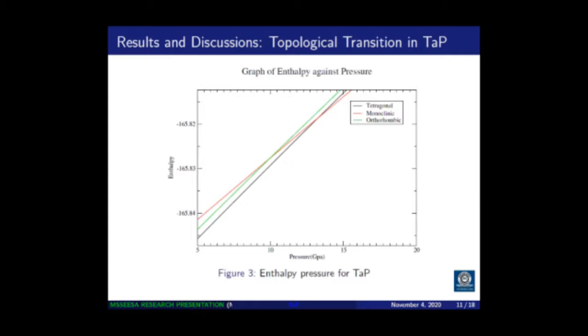And when I was doing so, actually there was no transition at that particular point. However, when I increased the pressure up to about 9.974 at this particular point, you can see that there are three graphs in this graph. We have the red for monoclinic, the black for tetragonal, and the green for orthorhombic. So when applied pressure of this region, about 9.97 gigapascals, you can see that here.